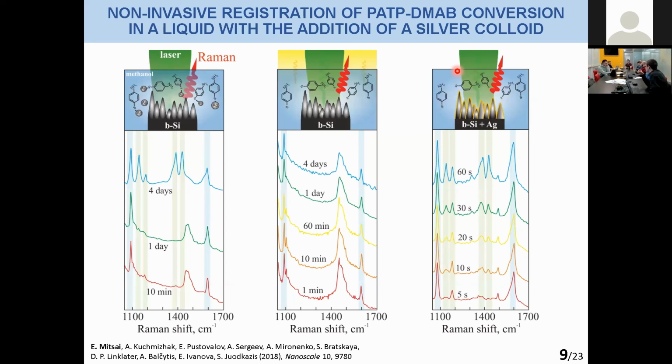Yeah, I think I had a similar question. This is the tricky part of SERS effects. If you just double the intensity of the laser pump, you don't get a dramatic enhancement. But if you increase the quality factor of the mode, you will get this power of 4 increase.